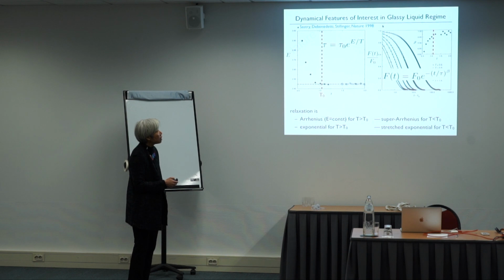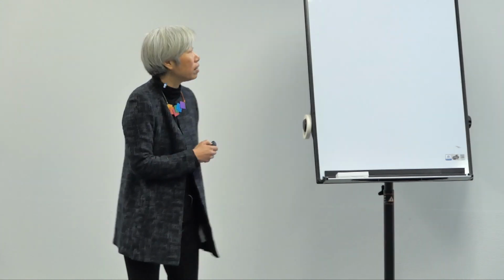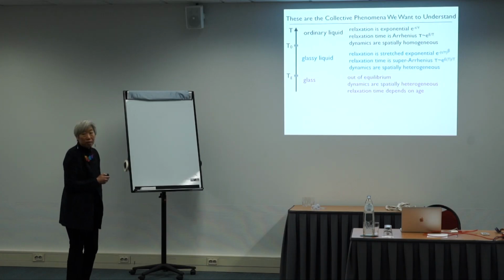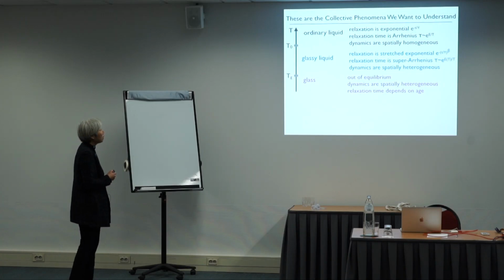It becomes stretched. And the temperature at which this drops is the same temperature at which you go from Arrhenius behavior to super Arrhenius behavior. That's the onset temperature. And where the dynamics become spatially heterogeneous is the same temperature again.